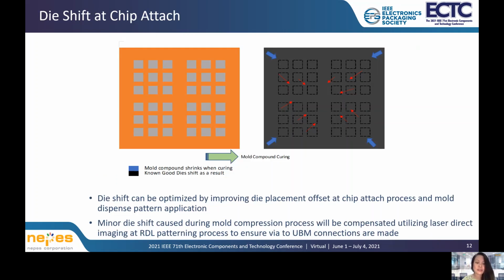One of the concerns during mold dispense process is die shift. Mold dispense optimization needs to be considered since mold material tends to shrink and gravitates towards the center of the panel. So I have here a little cartoon on your right hand side. Blue arrows show how mold tends to gravitate towards the center, and then the red arrows indicate possible die shift in X, Y, and theta direction.